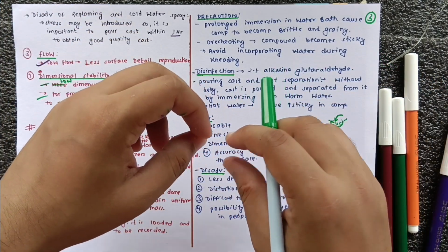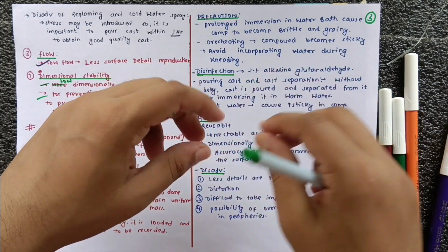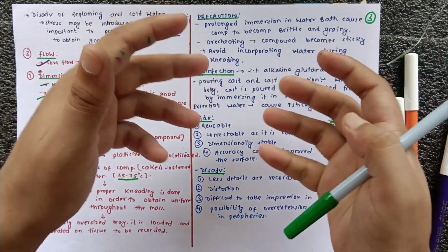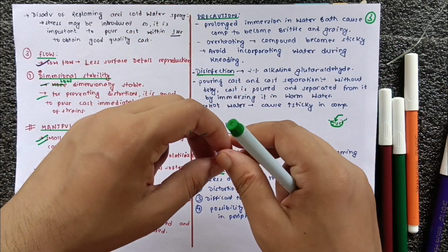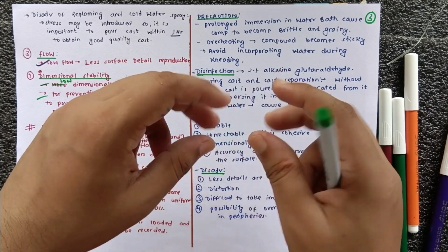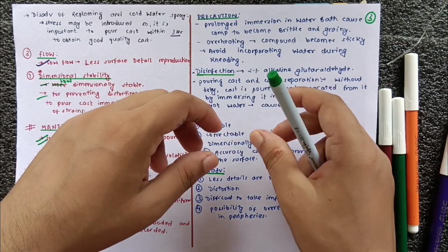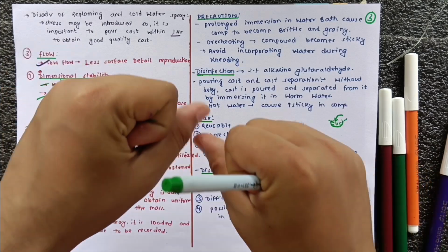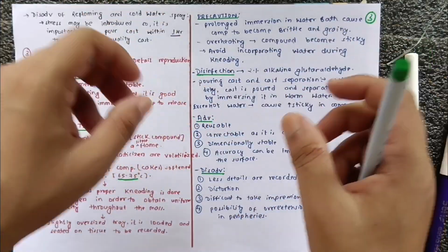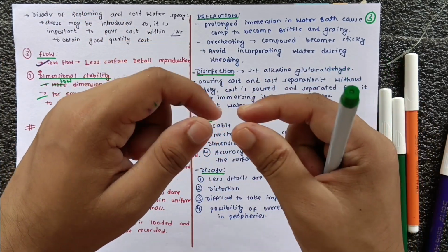So first we break the cake of the impression compound, we put that into this rubber bowl, and we wait for its increasing plasticity. With the temperature there is an increase in plasticity of this material, so it becomes moldable. After the fusion temperature, as it is moldable, we take it and again knead it. We take the substance from the periphery and push it into the center. So the surface substance would come to the center and the center substance would come to the periphery, so uniform plasticity would be present all over the substance.